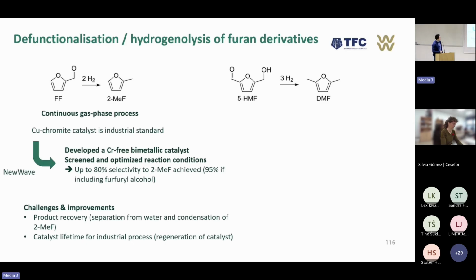Second is also the condensation of methylfuran. Methylfuran is a really volatile molecule, with a boiling point of only about 60 degrees. This process is usually done at low pressure, so it's not that easy to condense the methylfuran from the vapor phase, especially if you dilute it in hydrogen. So that's a challenge.